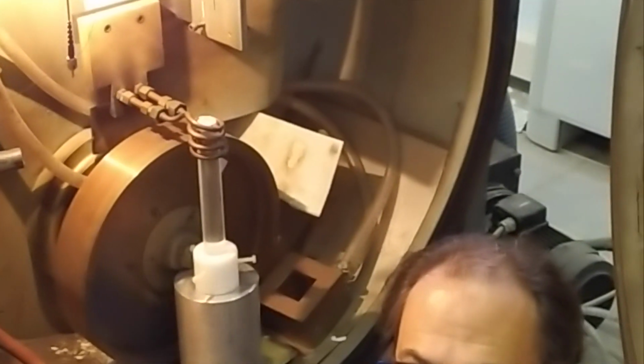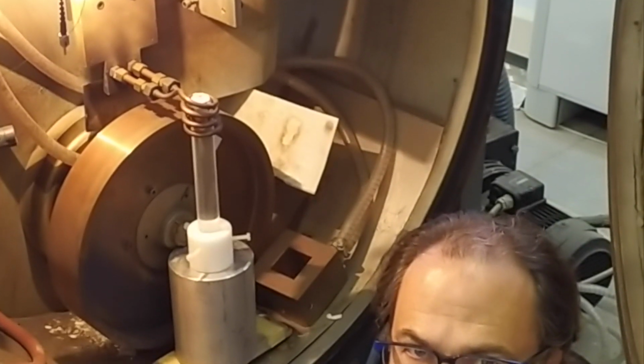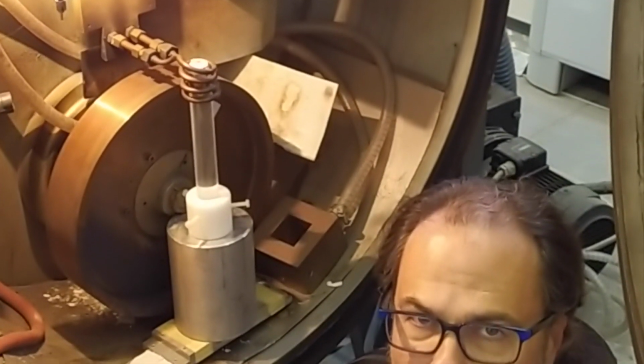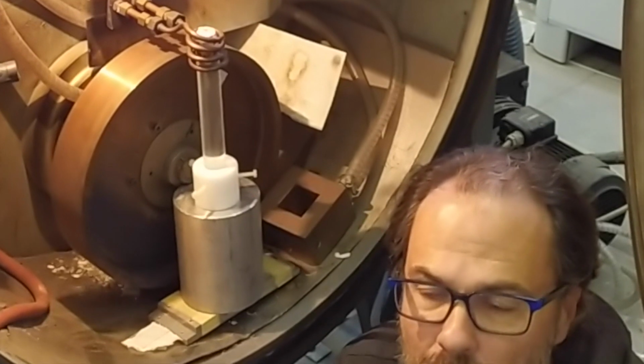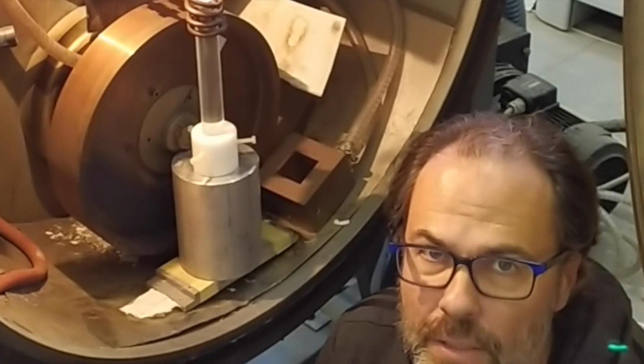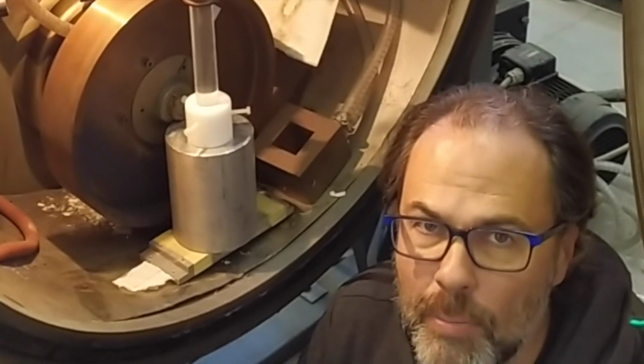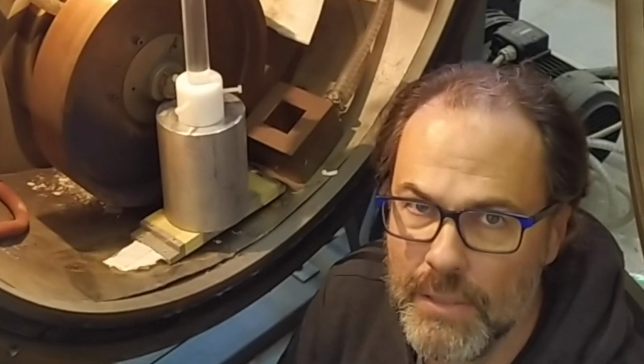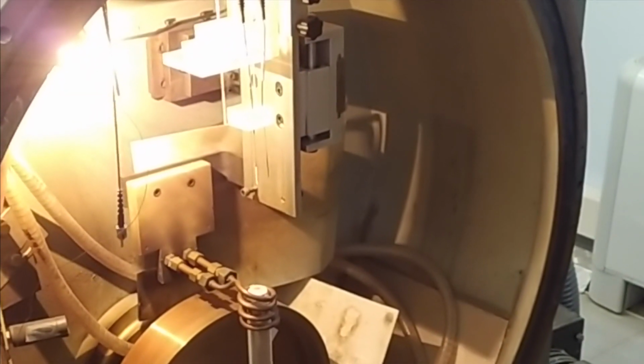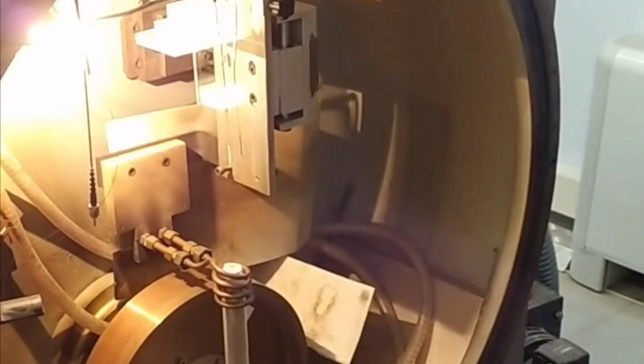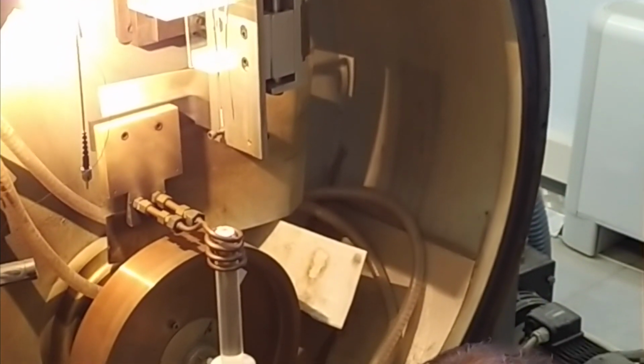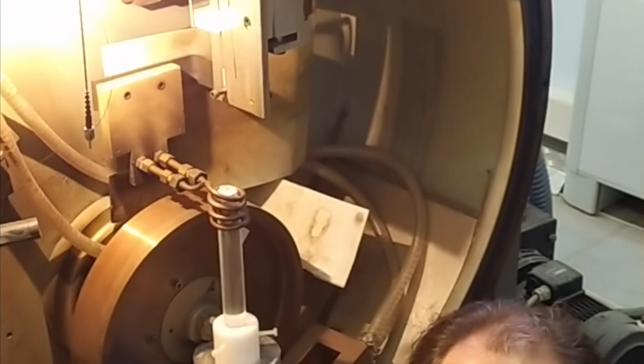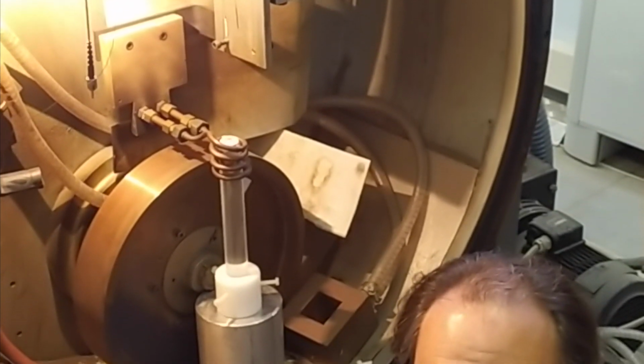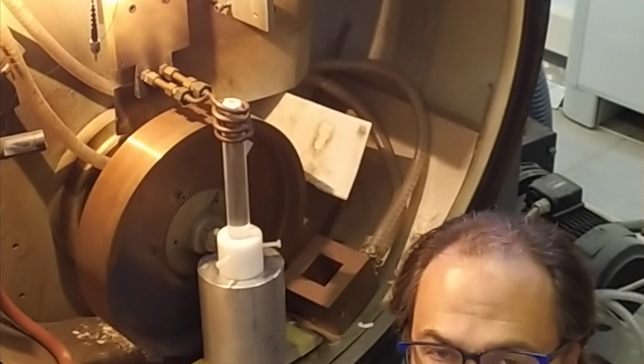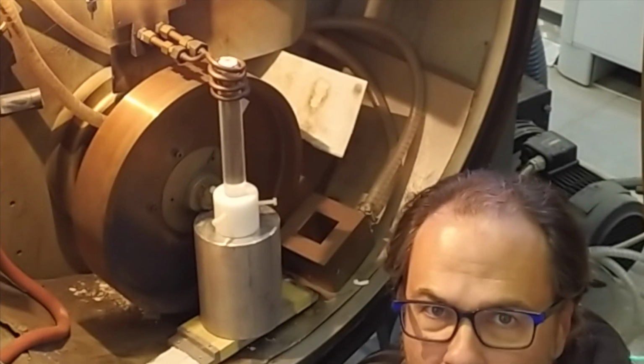When trying to develop this technique to treat cancer, the metrological challenge is to be able to accurately measure the heat that is generated by the nanoparticles when they are submitted to an alternating magnetic field. This task may seem trivial, but it is not possible to measure directly the temperature of the magnetic nanoparticles because of their size. Therefore, it is necessary to disperse them into a medium and measure the temperature of that medium.